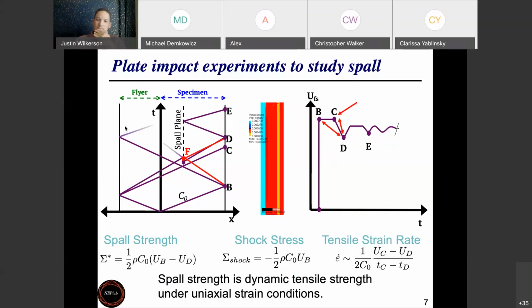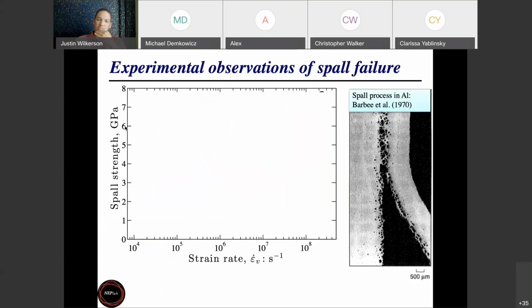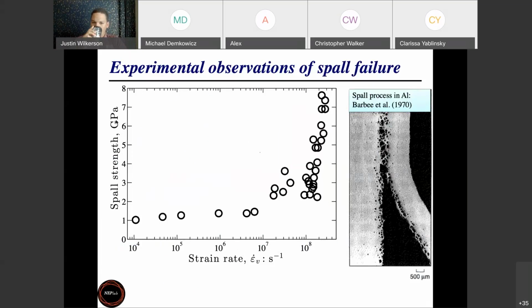Okay, so let's take a look at some experimental observations. I'm going to plot that tensile strain rate that you experience in the spall plane as it's ripping itself apart on the x-axis, and spall strength on the y-axis. We carried out a number of experiments on aluminum. This is a pretty ordinary aluminum, nothing special about it. But what you can see is at really, really high strain rates, on the order of 10^8 per second, this material can hold 6, 7, 8 gigapascals of tensile stress before it rips itself apart.